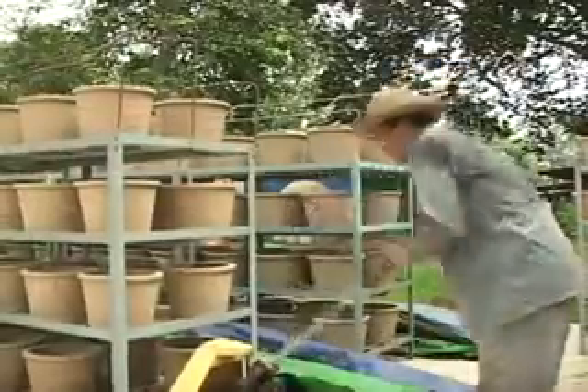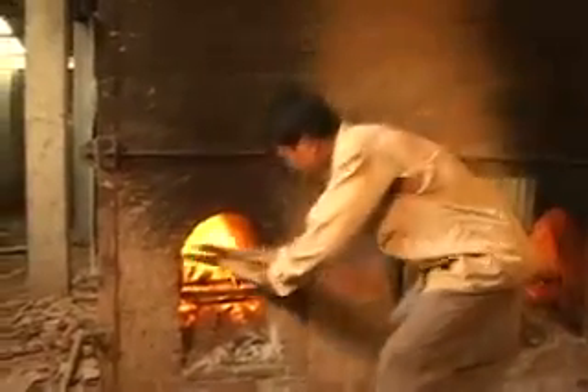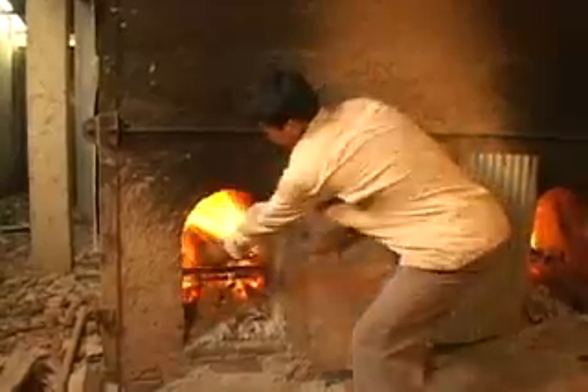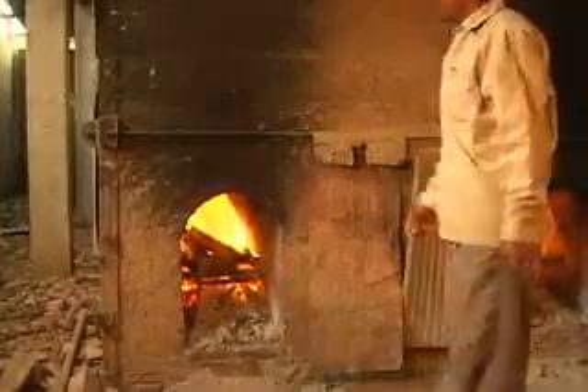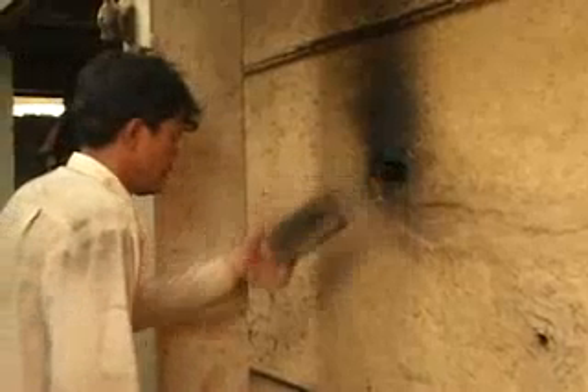Once the filters are dry enough, they are carefully loaded into the kilns. The filters are stacked inside the kilns in a special way to ensure there's even and thorough heat passing through them. 2 pyrometric cones are used inside the kiln to monitor the temperature. The kilns are heated to approximately 100 degrees Celsius for about 1 hour to drive off any excess water. Then the heat is gradually increased until the temperature reaches about 866 degrees Celsius. The first pyrometric cone melts at approximately 830 degrees Celsius. This alerts the person firing the kiln to begin monitoring the temperature very closely.